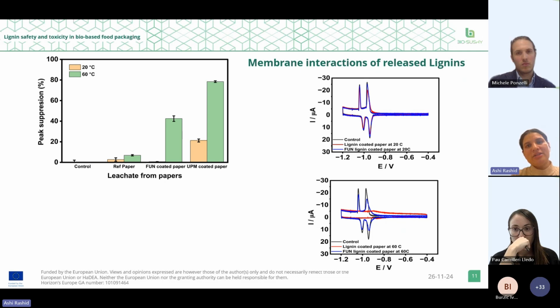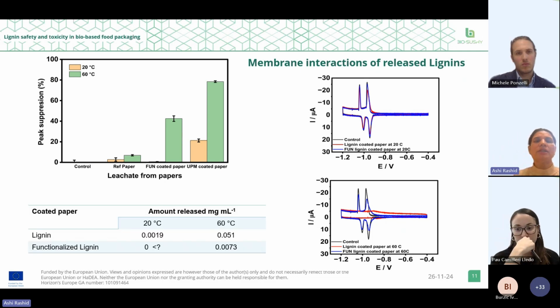When these leachates were analyzed using HPLC, we can see that functionalized lignin is leached to about 0 milligram per mil at 20 centigrade, and to a very little 0.0073 milligram per mil at 60. In contrast, the uncoated lignin has leached considerably at both temperatures.